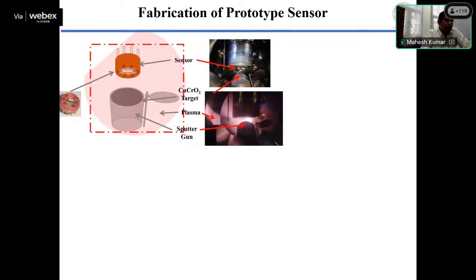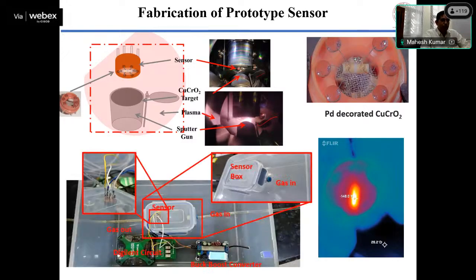So how are we doing this transfer? In the sputtering, we use this alumina tube and then do the deposition. Whatever thickness we deposited on SiO2, we optimized, and we use the same thickness here. All other parameters are the same. We deposit this copper chromium oxide material, and then we check the heater. We keep our temperature around 150 C.